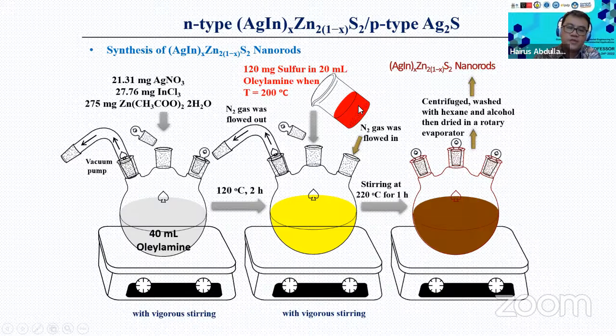Then we will form a very special color, like a black color. The red color is like a black color, and then we inject into the solution. Then we will form a brown color solution. Right. So after 220 degrees for 1 hour, we will form nanorods of AgInZnS. And then we do the washing procedure, centrifuge, and get the powder.